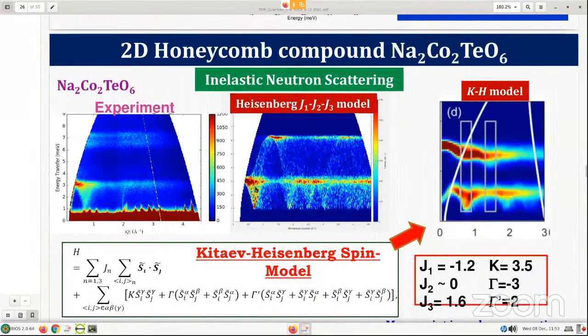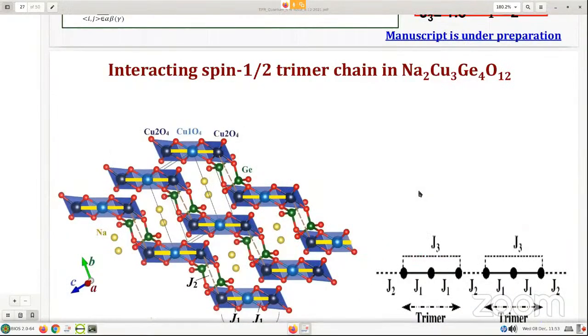We have also seen, at low temperature, a spin wave, and we have taken this kind of Hamiltonian, done the modeling, and determined the values of J1, J2, J3. And you see the K term is very much there, 3.5, and cannot be neglected. So from this we can conclude that both Heisenberg as well as Kitaev interactions are very much present with this cobalt 2 plus, which forms the honeycomb lattice, and it is close to the J equal to half ground state.